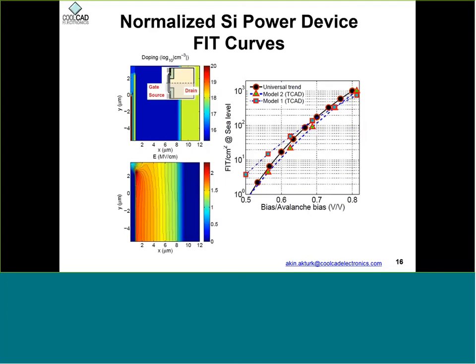So what we do is, once we characterize it, we can use these models in TCAD simulations and get a very zeroth order approximation of the failure in time curve for any hypothetical device. But this is a very rough estimate, so in general all devices need to be tested for this application. And then we can get exact numbers for a particular device, which is going to depend on how you design the device, and also, for example, if the device is a punch-through device or a non-punch-through device, you get different failure rates or bias-dependent curves. So we can simulate and get some zeroth order approximations using our first order estimates, and then measure them later on to see how well they match.